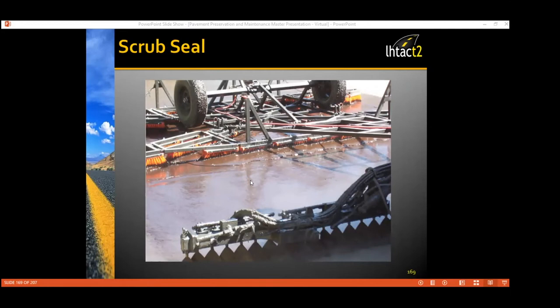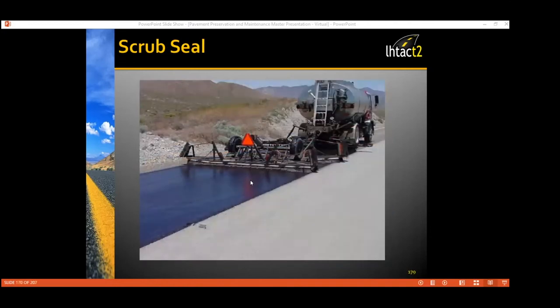I gave this workshop a little earlier in another part of the state, and somebody actually tried this scrub sealing technique on a test section of roadway, and it did not go well for them. It ended up being a goopy, gloppy mess. A lot of the asphalt ended up going off the roadway. They had a hard time putting the sand down. It turned into a messy operation. They did have to agree that if you've got a lot of small cracks, by scrubbing this stuff in, it did take care of sealing those cracks, but they said they would not use it again. So just an FYI.